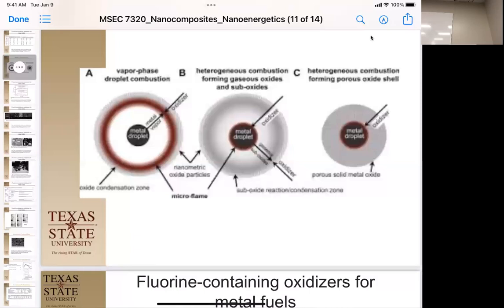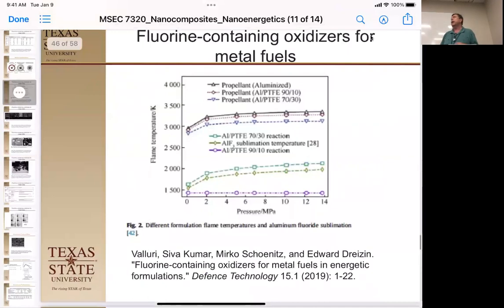However, if your oxidizer or the thing that is oxidized starts forming a crust, if it's a permeable crust, you'll still keep burning through until the end. However, if it's an impermeable crust, you never burn all of your material. So having those high melting oxides like tungsten oxide and stuff like that makes it very difficult to burn all of your material. So that's one of the reasons using these fluorine materials is really good, because the outgassing part